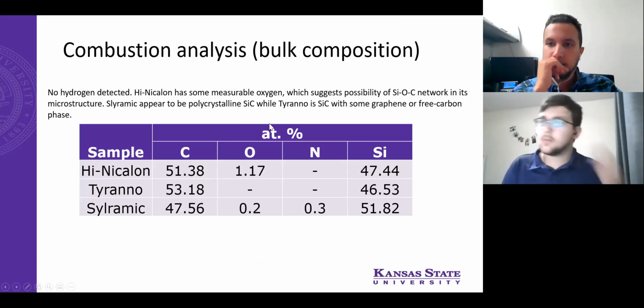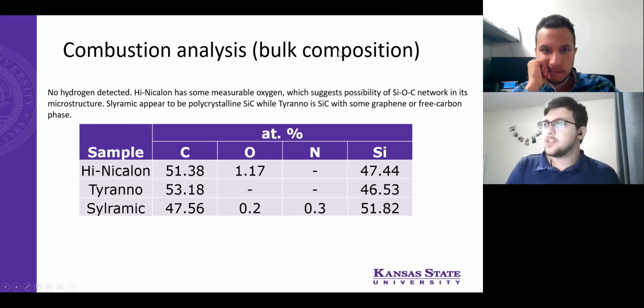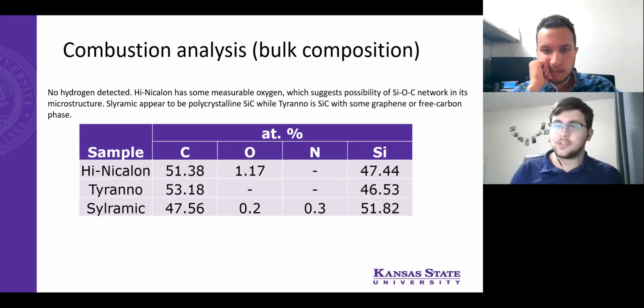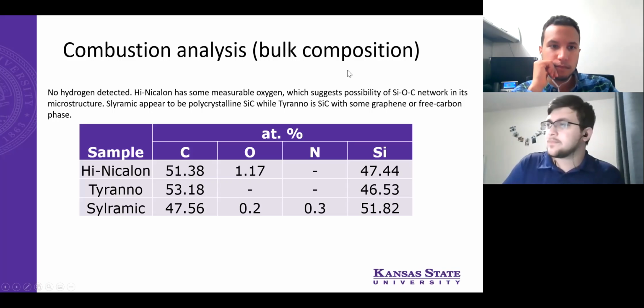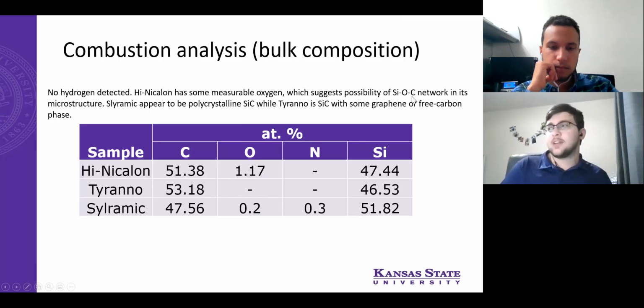So jumping back in here, the combustion analysis was to test the bulk composition, meaning throughout the fibers, whereas the Raman was just a surface analysis. So we can see the presence of oxygen in the Sylramic and the Hi-Nicalon, which might suggest the possibility of an SiOC network.